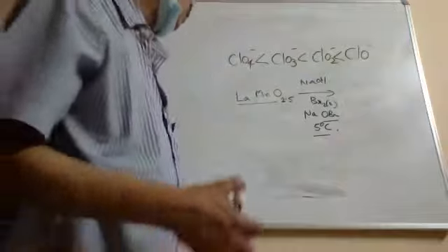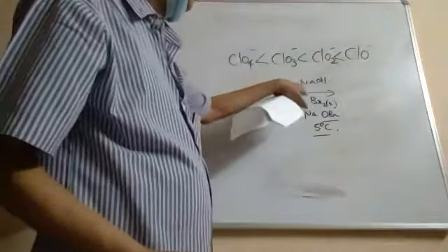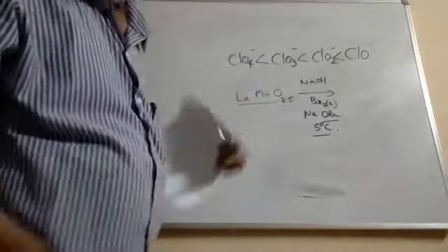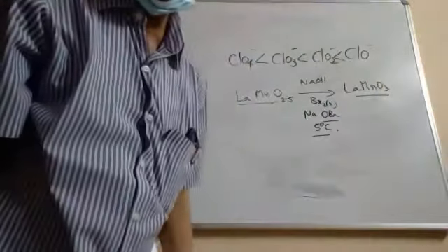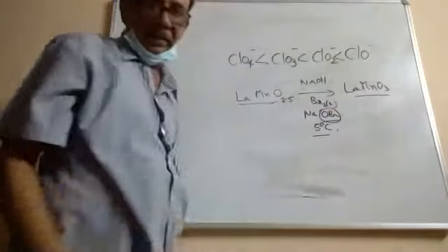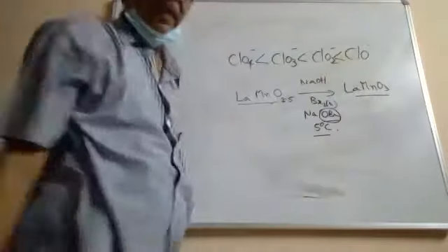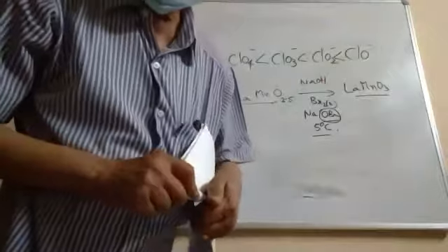So instead of using violent ozone and oxygenations, you can use simply a mixture of sodium hydroxide and bromine at 5 degrees Celsius and stir it with this compound. And after about 3-4 hours, you get LaMnO3, which means this compound is now oxidized, which implies that OBr minus is reduced. So since OBr minus, just like this, is easily reducible, we can have soft oxygenation processes.